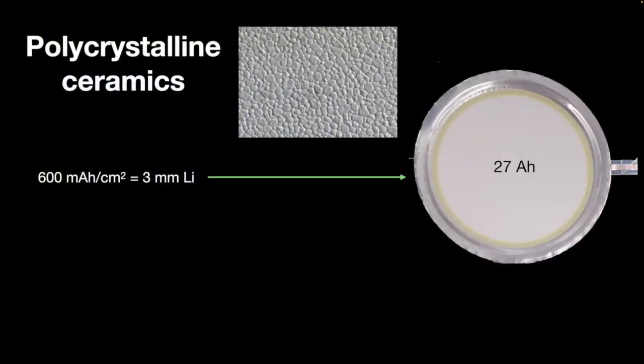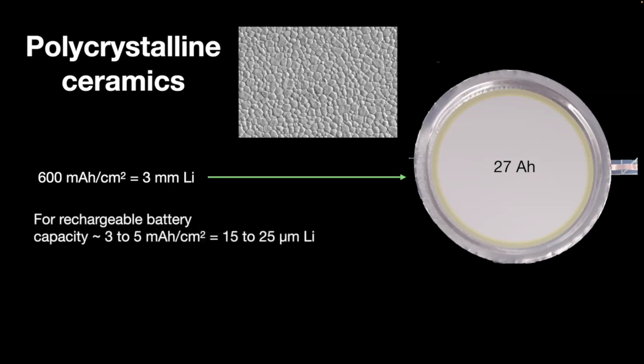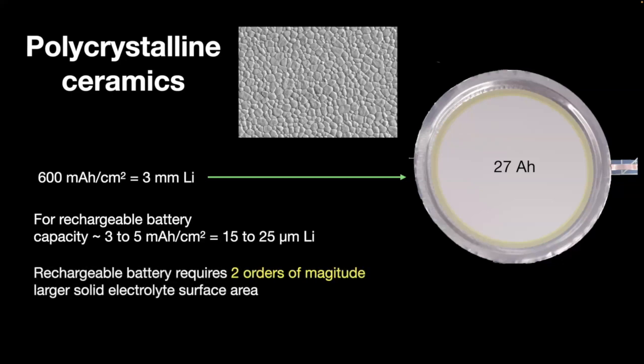So again, going back for a second to these choices. Obviously we have a lot of experience with polycrystalline ceramics. We have a product based on ceramic membranes. But if you go from single use to rechargeables, there's a rather dramatic shift in the amount of capacity per unit area. What does that mean? It means that the rechargeable battery is going to require two orders of magnitude more surface area for the solid electrolyte. So that solid electrolyte had better be pretty inexpensive.